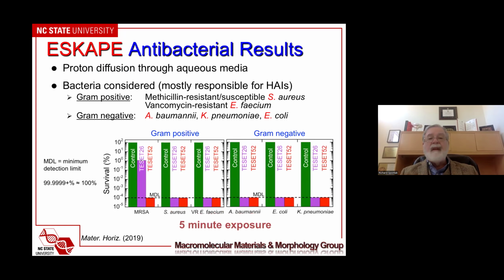But you'll notice that in all cases, for the 52 mole percent polymer, we get to the minimum detection limit within 5 minutes. And we can boldly claim that 99.9999% plus, because we can only measure to 10 to the minus 4 down here, is about 100% kill.